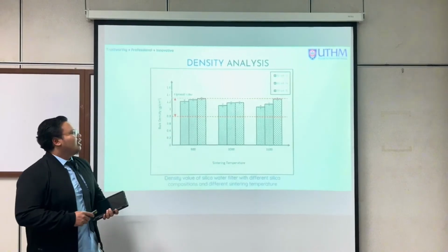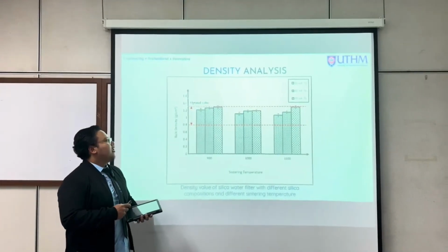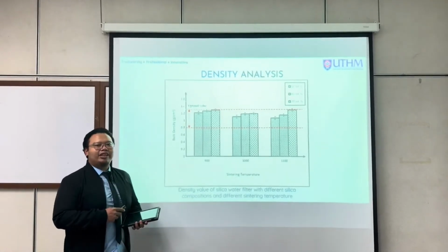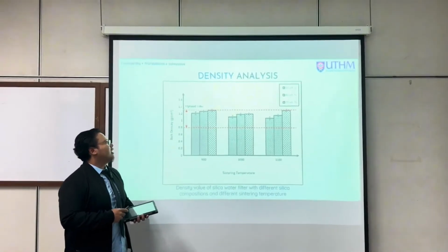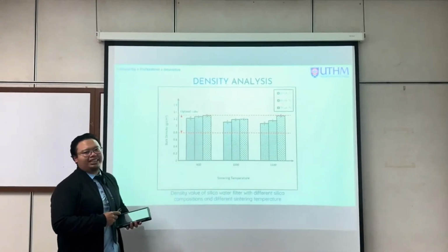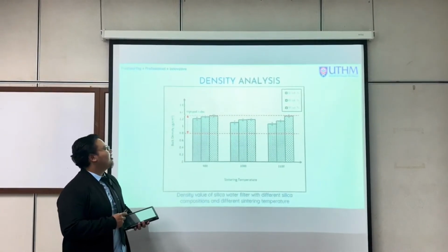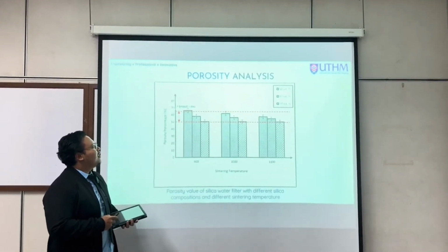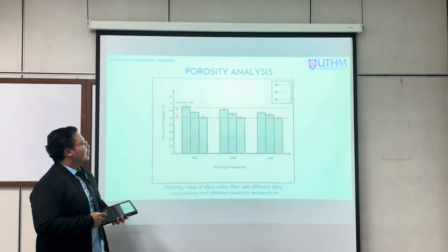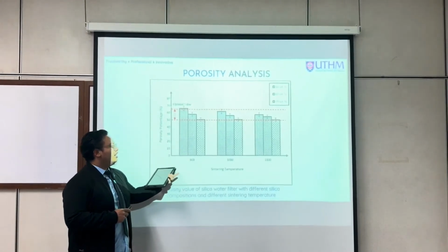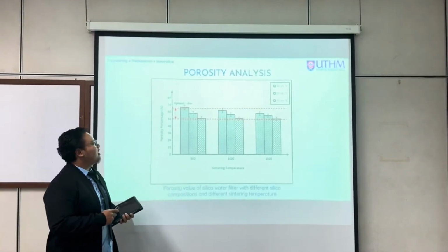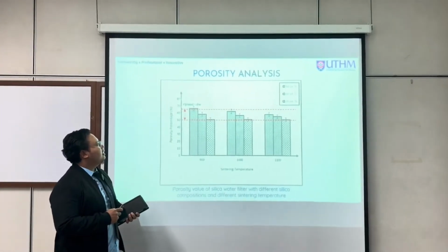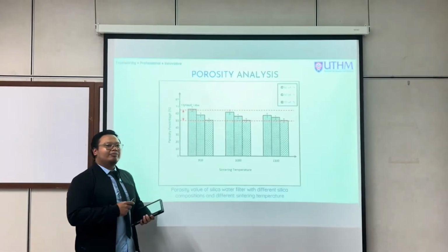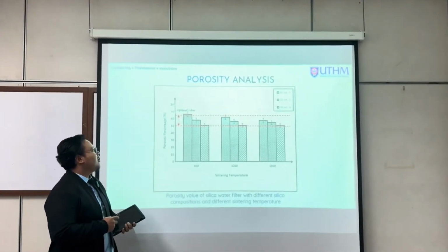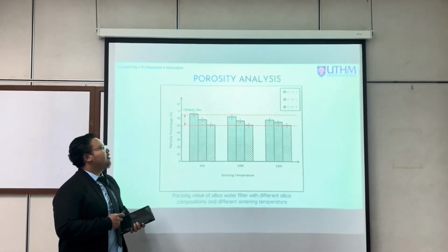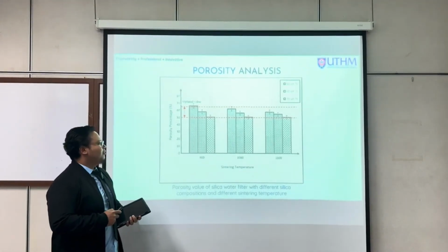For density analysis, we can see that all samples have reached the optimal range for the fabricated silica water filter, which is from 0.8 g/cm³ to 1.3 g/cm³. For porosity analysis, we can see that 50 weight percent of silica from 900 degrees Celsius exceeded the optimal value for this fabricated silica water filter, which ranges from 50 to 65% porosity.